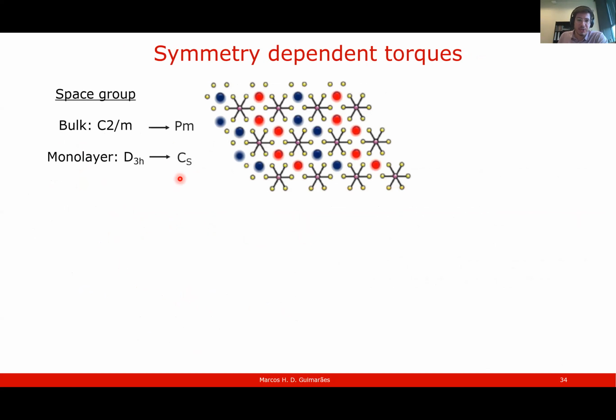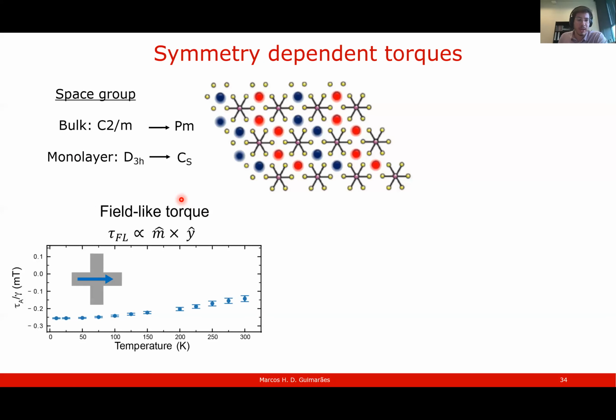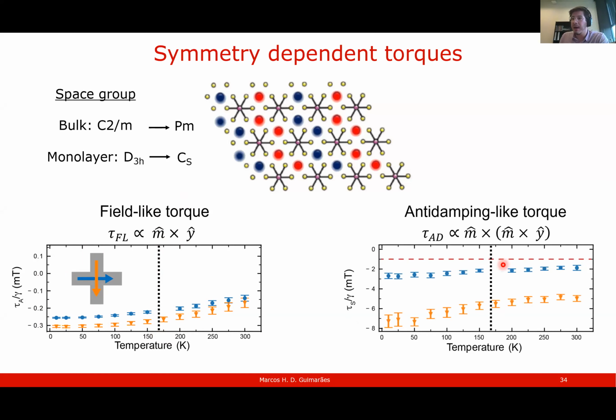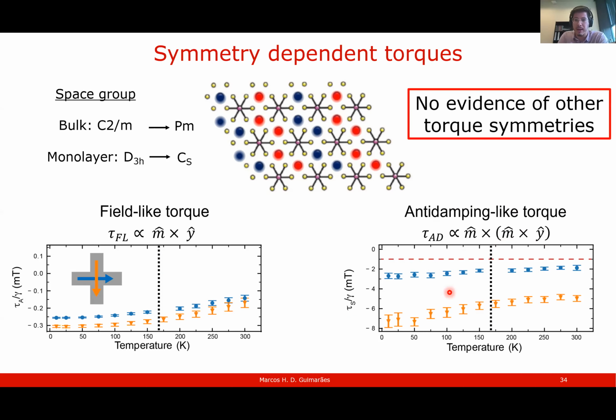Now let's look if there is any symmetry dependence. As we cross down the Néel temperature, we have a change in the space group. And if we apply the current in different directions, or apply the current in one direction, we get the torque efficiency as a function of temperature for the field-like torque. If you apply the current 90 degrees oriented to it, then we have a small change, and this doesn't seem to change much as we cross the Néel temperature indicated in the dashed line here. If you look at the anti-damping-like torque, this has a little bit of stronger difference, but still we don't see very strong indication that the magnetization is playing a role there. So we have to explore this a little bit better.